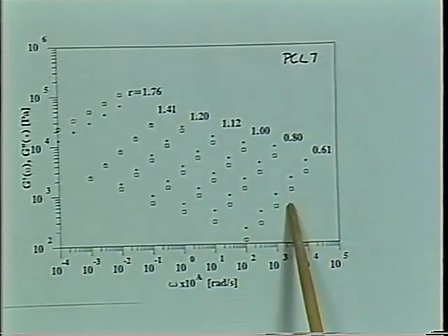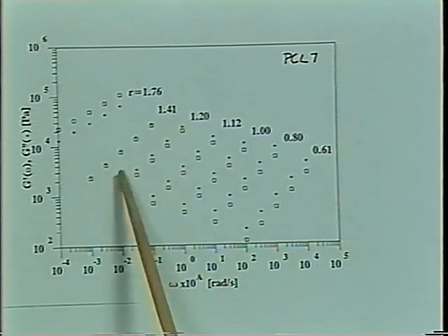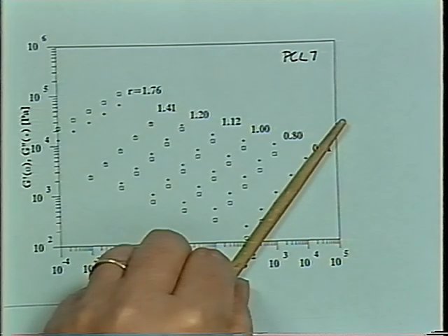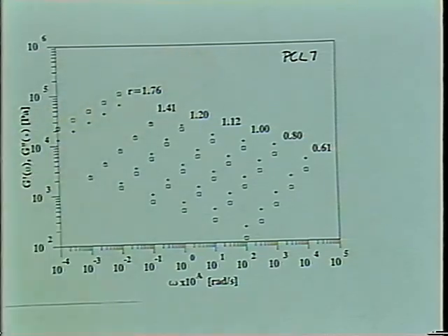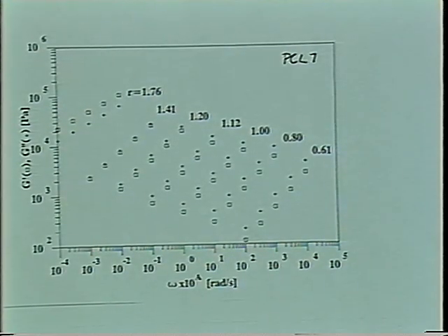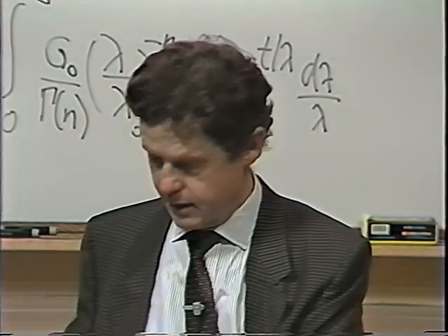He just has a set here, a different stoichiometry. And you can see that the slope n changes, it is very large here, and it's smaller if R, the extent of reaction, is very high. And again, with stoichiometry, you see a relation coming through here. And everything fits together very nicely.